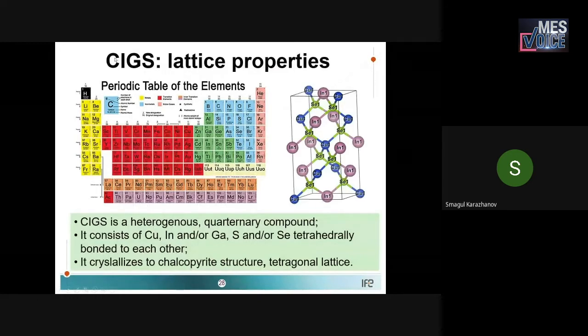Then the other candidate is CIGS solar cells: copper, indium, gallium, sulfide. It's a heterogeneous solar cell, a quaternary compound. Its band gap can be tuned from 1.1 to 1.9. And its efficiency nowadays is above 20%, but as you see, there are 4 different compounds and elements here. And it's very difficult to get pure material.